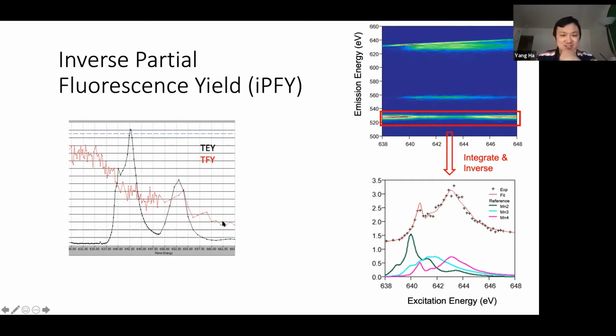This is because we also have oxide, and the signal from the oxygen emission will distort our fluorescence signal, which, if we use the traditional TFY method, we got nothing. So what we can do, we can get help from our RIXS. So we can take the 2D map of the RIXS for the manganese.